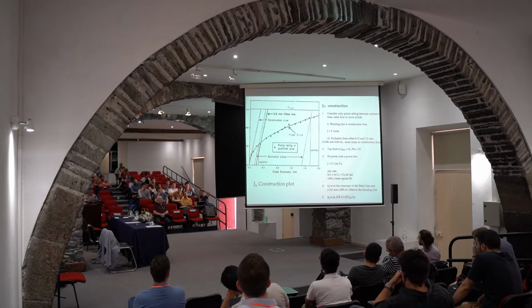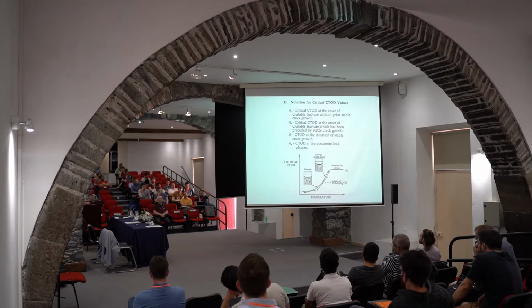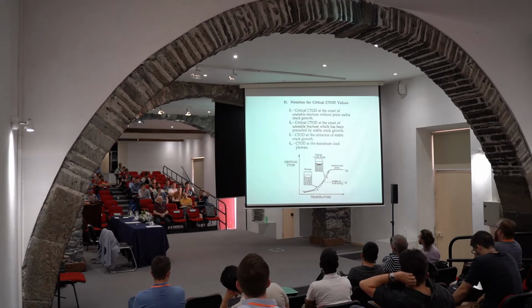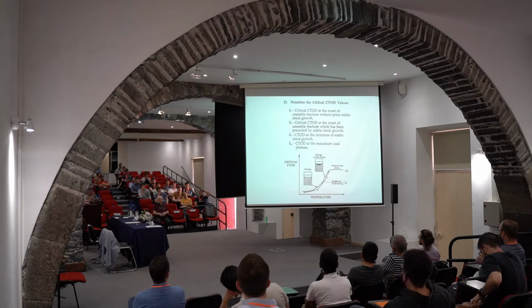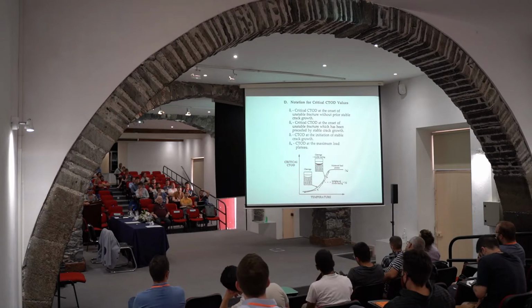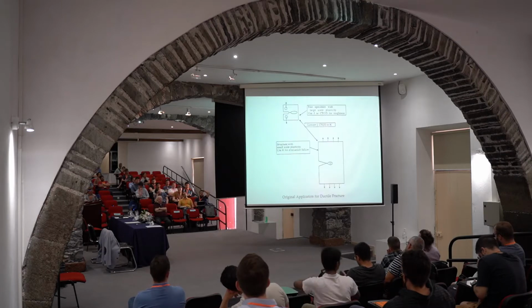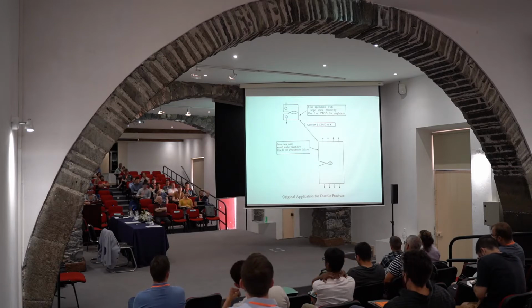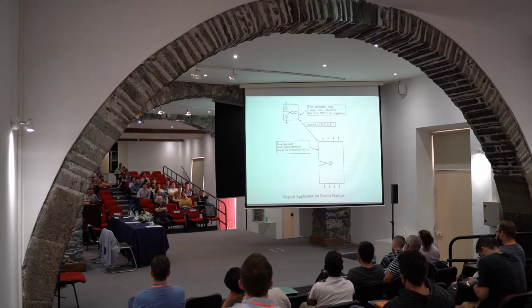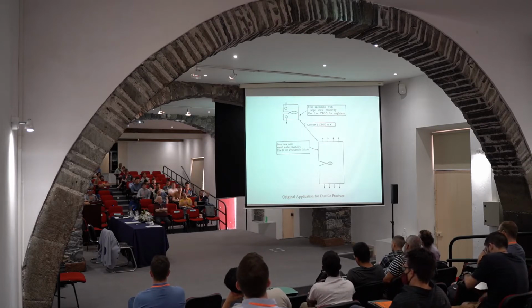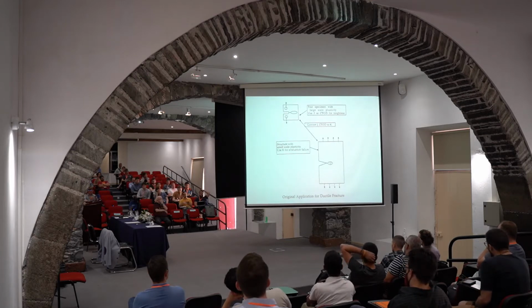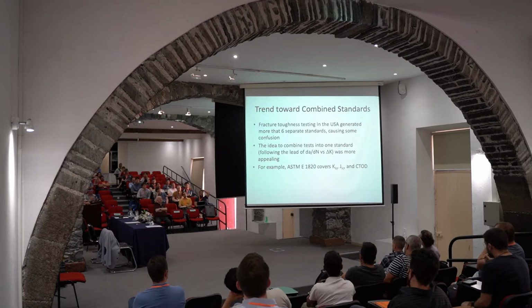I'm now trying to run faster because we lost a bit of time. And the same story is about crack tip opening displacement. There is this critical value at the onset of unstable fracture. Then delta U is without crack growth, this is with stable crack growth. Delta I is at the initiation, and delta M is at the maximum growth plateau. These more or less follow the same story as J integral. So all these facts we should know, so that we know what we are actually doing when we are transferring our test results to the real component. And I think that is one of the last slides in this first part.